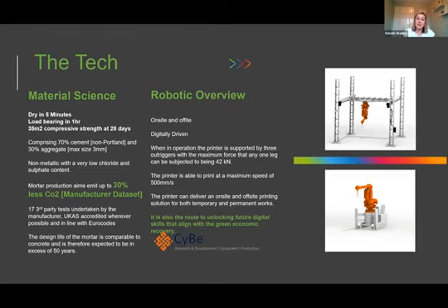It's not a metallic, it's low chloride and sulfate content. So from our perspective as a sustainability driven business, we want to make sure that we're bringing materials into the process which are at this point in time the most environmentally friendly they can be. And the manufacturer data set points towards 30% less CO2 than a standard concrete mix as well. So these for us point us in the right direction of why we'd be wanting to integrate these types of materials. There is a lot of third-party testing that's already happened through the manufacturer, through UKAS accreditations and using Eurocodes.